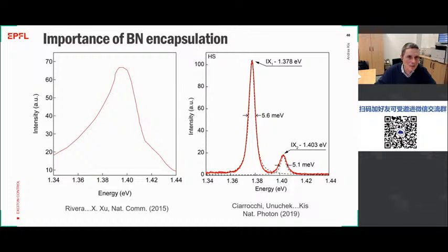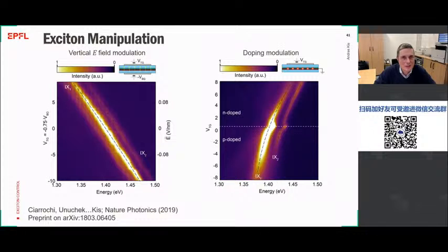And now in this device, since we are talking about the device, we can also apply electric fields and change the doping levels, and this can then tune the light emission coming from this excitonic device. By applying a vertical electric field, we can change the energy of the electric dipole and the energy of the exciton, and this corresponds to just a simple Stark effect. That's the polarization times electric dipole times electric field gives you the change in energy. So as we change the electric field, we can tune the transition and the energy of these excitons, and then they emit at different energies because we change their energy using the electric field.